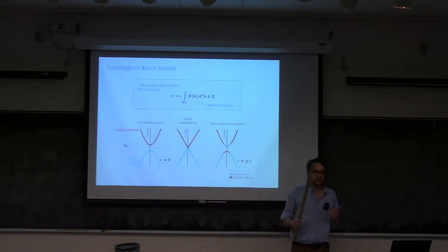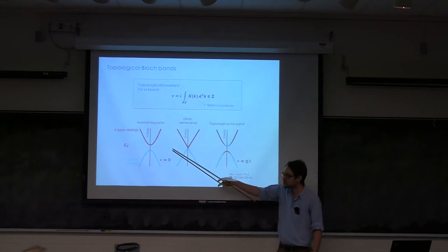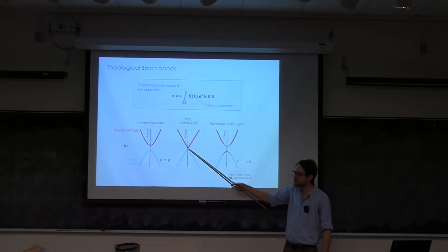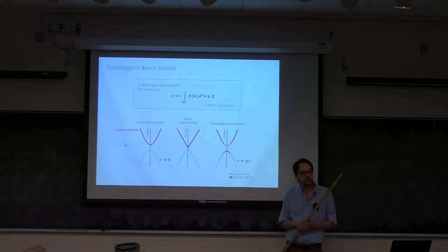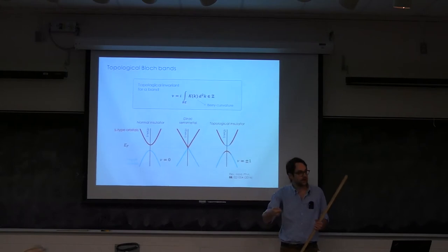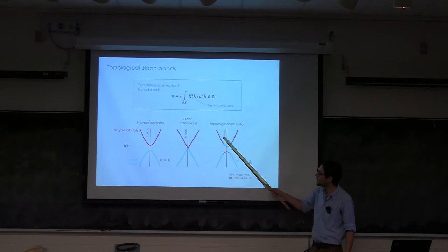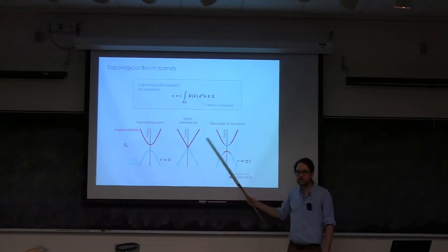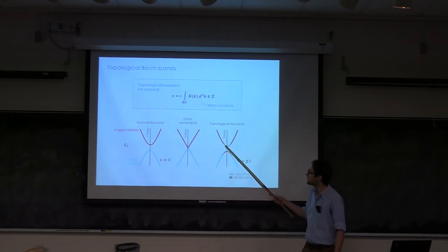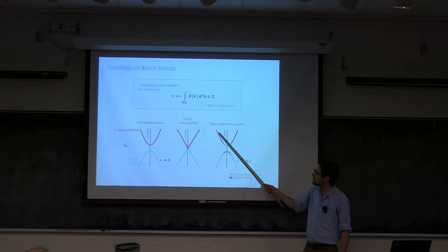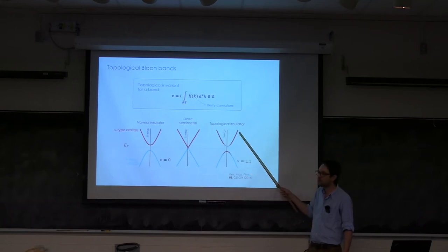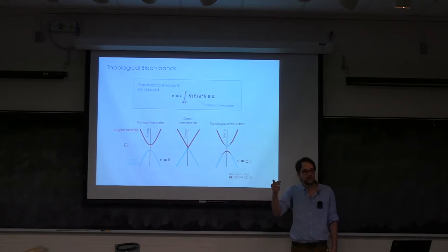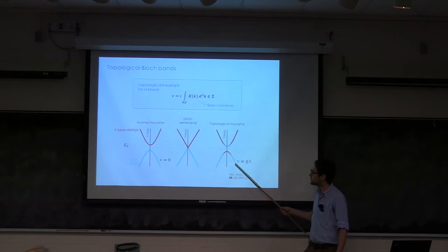Now, if we start to perturb this crystal by introducing, for example, spin-orbit interaction, what people have shown is that we can change this band structure. We can perturb it, we can close the energy gap. And if we continue to increase the spin-orbit interaction, let's assume that it's a knob that we can tune at will, we end up with reopening the gap with now a band structure that has these eigenfunctions. So you look, the energy is the same. If there were no colors, these two band structures would be the same, but the color is drastically different. Here, at negative value of momentum, you have S-type electrons, and they move to P-type, and they go back to S-type. So you have a winding of the symmetry properties, and you have the complementary in the valence band. So somehow they have exchanged symmetry properties inside.